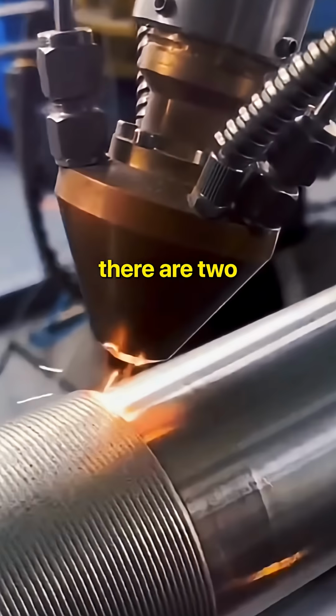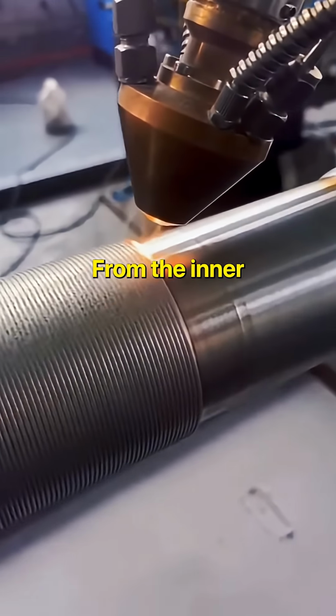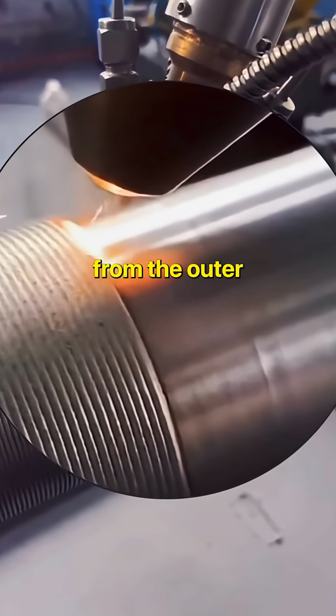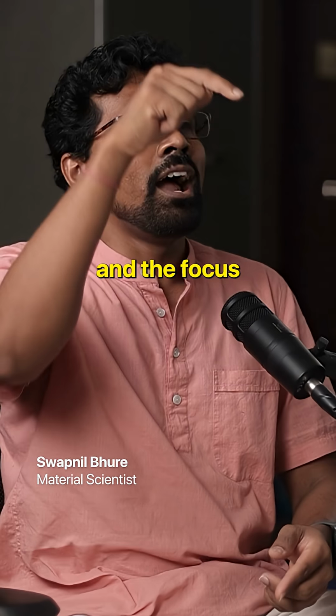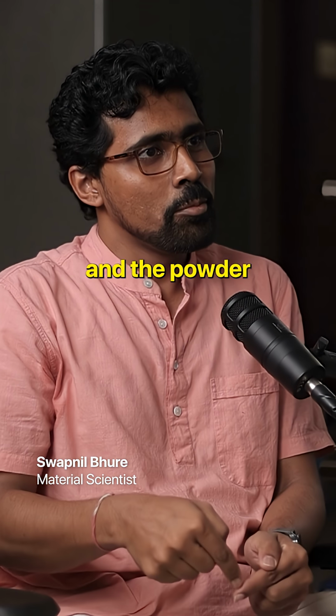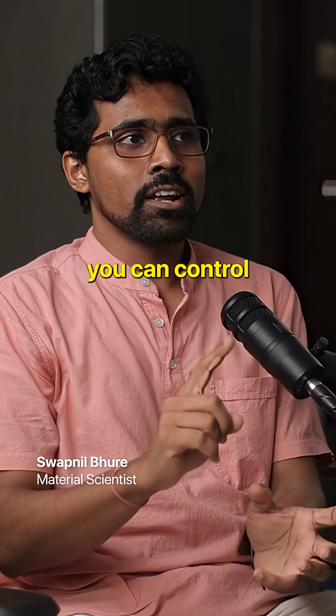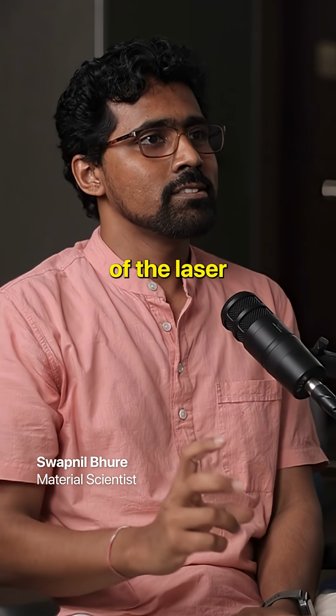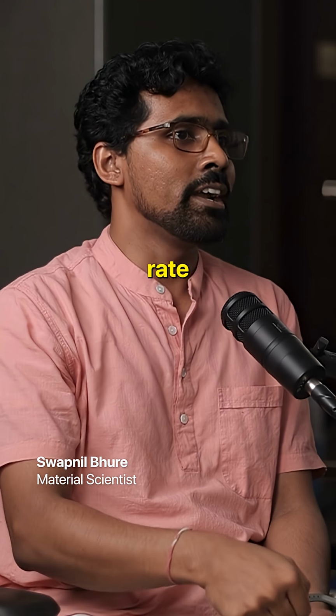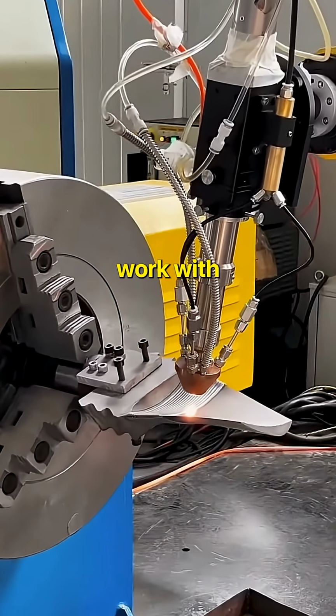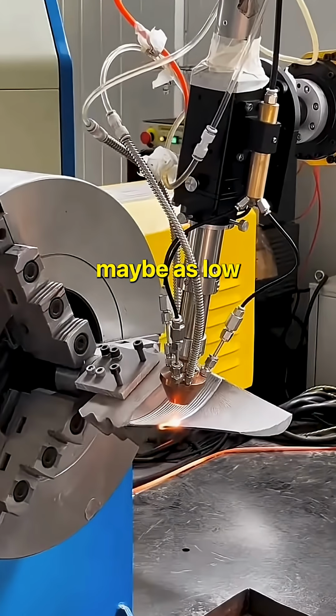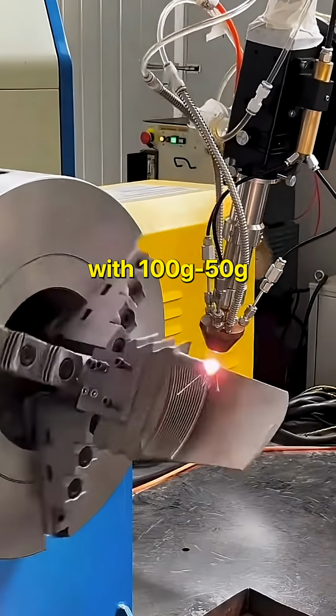So what happens is there are two coaxial nozzles. From the inner nozzle, the laser comes. From the outer nozzle, the powder comes. The focus of the laser and the powder is the same. So you can control the power of the laser and the flow rate of the powder, and you can work with very little powder, maybe as low as 100 grams, 50 grams of powder.